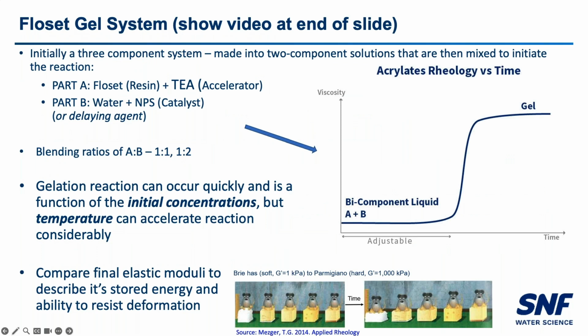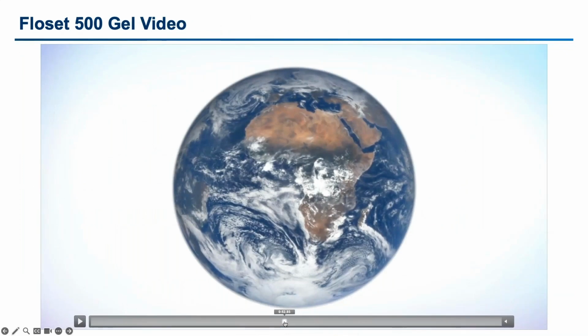So mention you've got the part A added together. Sometimes we get a gel formation. What I want you to look at here is just a little schematic at the bottom. It just puts it in perspective of cheese, actually. So if your brie cheese has very soft elastic modulus, 1 kilopascal, all the way to Parmesan, which has a harder elastic modulus, maybe 1,000 kilopascals. That's sort of our reference in terms of what we're looking at for the Floset. So I think there's a short video now that just shows this reaction in actual time.